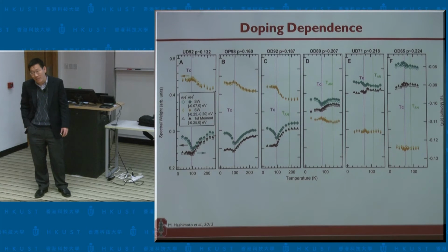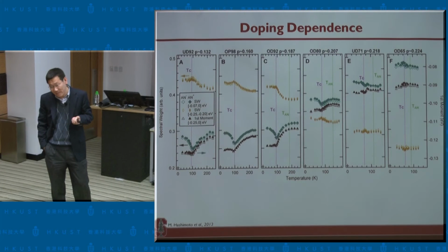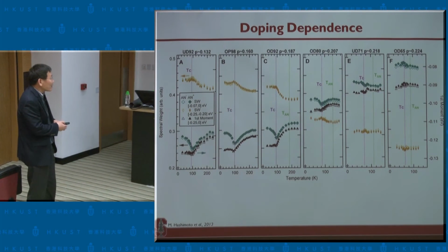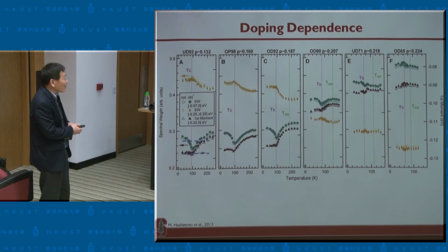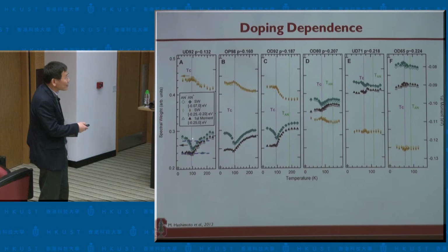The pseudo gap is only partially gap. Of course, a D-wave superconducting gap has a node also. Okay. So if I would do that, then you will see that I can take this as a plot, and then of course you can see that as I increase the doping, the magnitude of this singularity decreases, right? And of course, overall low energy spectral weight increases and high energy weight decreases. But what is important is to look at this singularity change, it decreases.